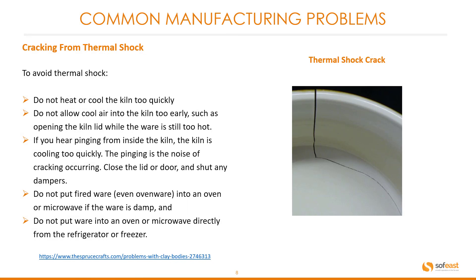Cracking from thermal shock: to avoid thermal shock, do not heat or cool the kiln too quickly. Do not allow cool air into the kiln too early, such as opening the kiln lid while the ware is still too hot. If you hear pinging from inside the kiln, the kiln is cooling too quickly.